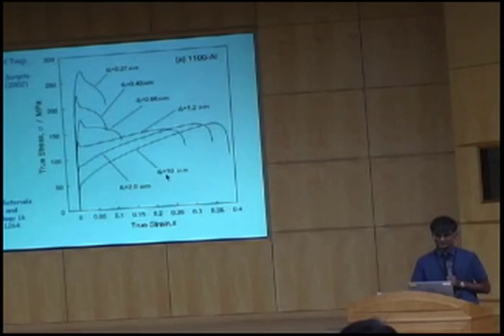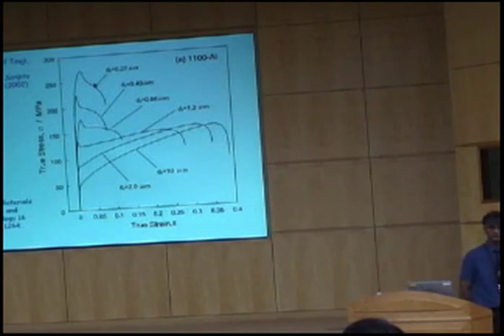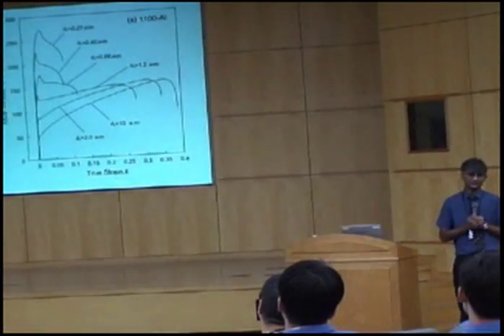Supposing we reduce the grain size from, say, 10 micrometers to 0.27 micrometers, of course we increase the strength. But look at what happens to ductility. The ductility almost vanishes. As soon as you start to deform, you get plastic instability. There's no uniform strain that you can see in that fine grain structure. And that's because the material loses the capacity for work hardening. If you have a very fine grain size, the dislocations go into the grain boundaries. So the inside of the grain is free of dislocations. So there's no capacity for the material to work harden. And you need work hardening in order to get uniform strain.